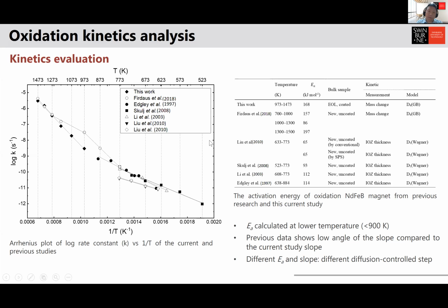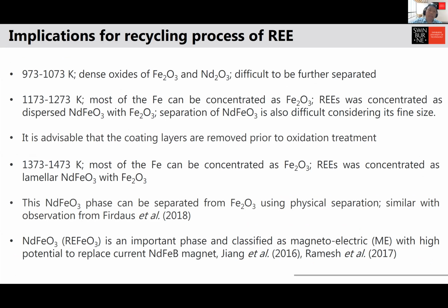So that gives us some sort of summary and the implication of this coating to the recycling process. So basically we should remove this layer first if we want to effectively oxidize the magnet, especially at low temperature. But if you want to do it at higher temperature, then it's okay. It's the same. However, we don't know the effect of nickel and copper on the NdFeO3 yet, whether that's a good effect or bad effect. But definitely some of the nickel comes into the REFeO3. So we don't know whether that's good or not.